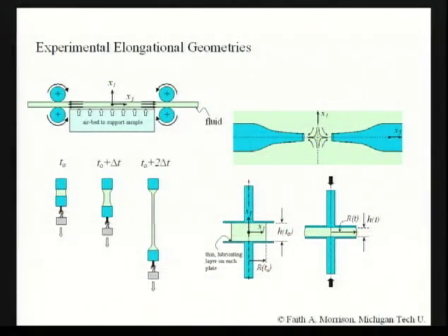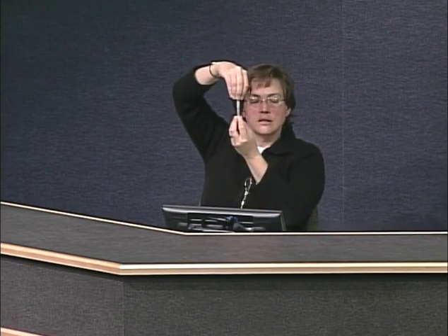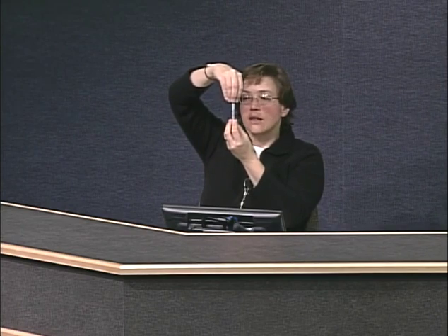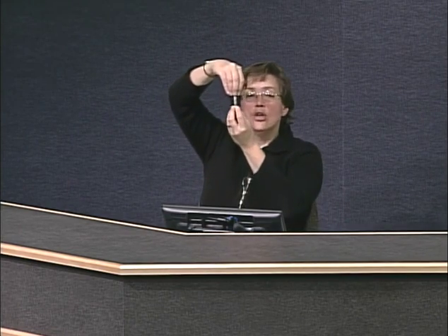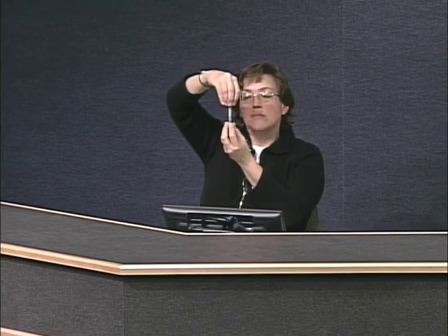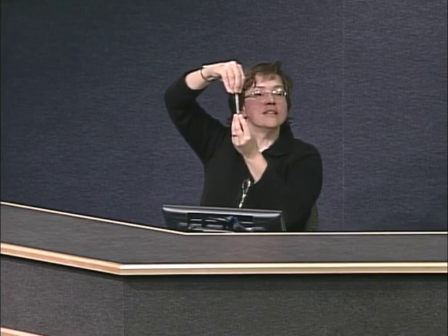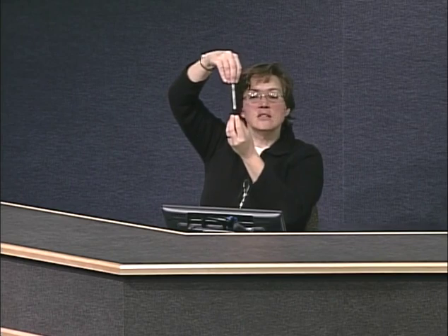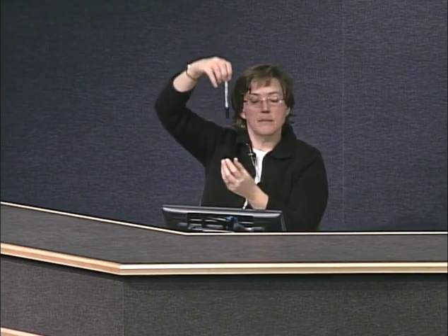How do we produce this flow in the laboratory? Very difficult. The Instron tensile tester does not do this flow. With the Instron tensile tester, you can put a cylindrical piece of a metal or a plastic into it, and you can move them apart. But to move them apart according to the velocity field that we just picked, I'm going to show in a second, you must move them apart exponentially fast. The Instron tensile tester grabs onto two ends of a polymer and holds onto them and doesn't let them deform. And we need those ends to deform just as much as everything else is deforming.